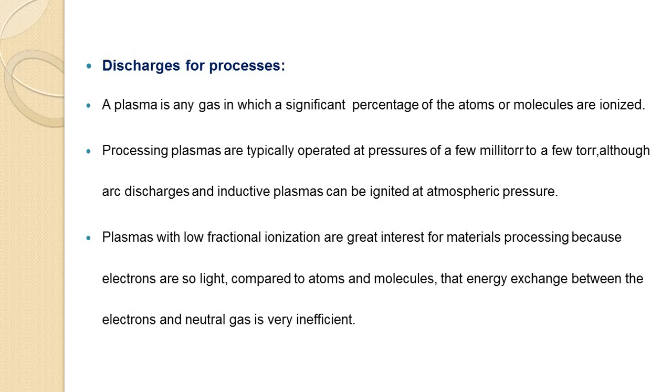The potential across the sheath surrounding an electrically isolated object, that is the floating potential, is typically only 10 to 20 volt, but much higher sheath potentials are achievable by adjustments in reactor geometry and configuration. Thus, films can be exposed to energetic ion bombardment during deposition.